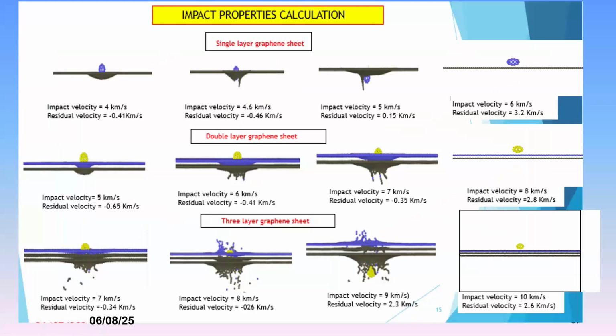So in my work with single layer graphene, double layer graphene, triple layer graphene, we impact that ball impactor at 4 kilometer per second, then 4.6, and then 5 kilometer per second, and 6 kilometer per second. So at 6 kilometer per second it breaks the graphene sheet. As well as in case of the double layer, we apply 8 kilometer per second, then it breaks the graphene sheet. And in case of the three layer, at 10 kilometer per second, it breaks the three layer graphene sheet.